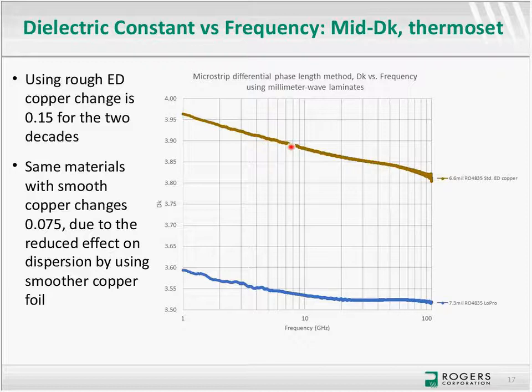So when you're using a material in your design software for a simulation, you have a value and you're using the same material, but now you're using a smoother copper, that actual dielectric constant for better accuracy of model versus measurement will change because of the roughness of the copper, even though the dielectric itself does not change. So you can see that from the value of this particular material, in this case the RO4835 material. With the smooth copper, it is a lower value of about 3.55 at 10 gigahertz, while it's about 3.8 with the rougher copper at about 10 gigahertz for this material itself that's being evaluated here.